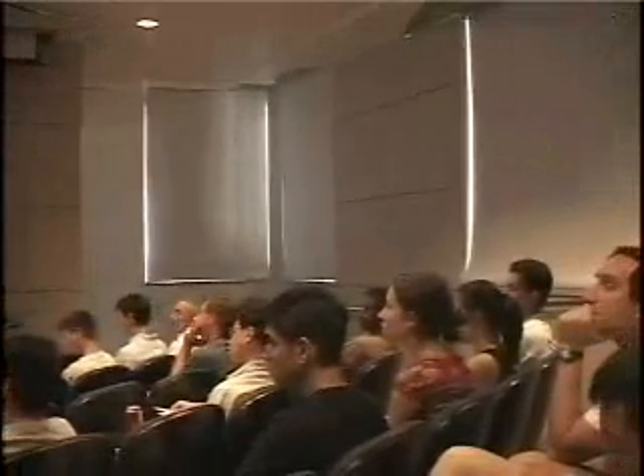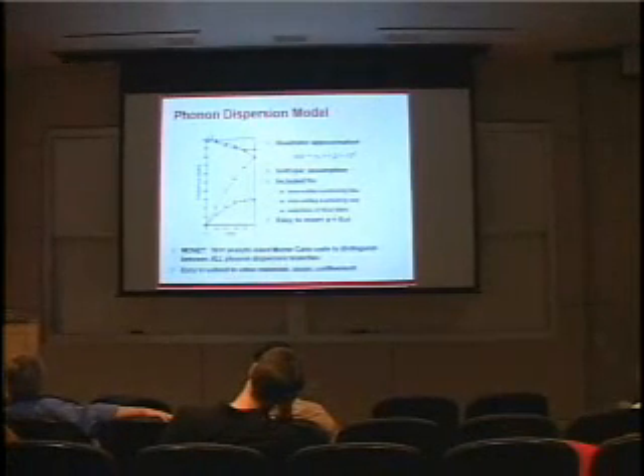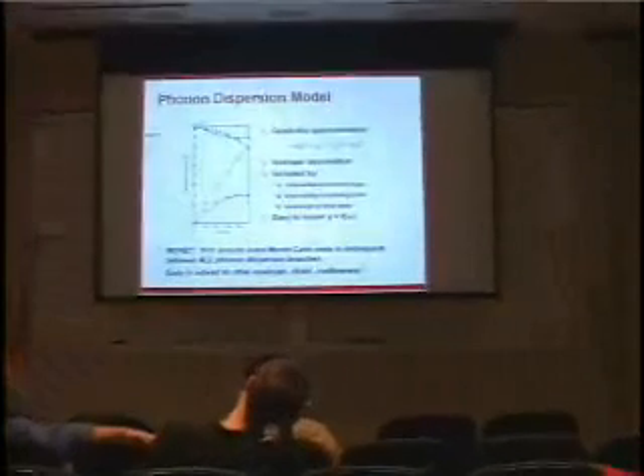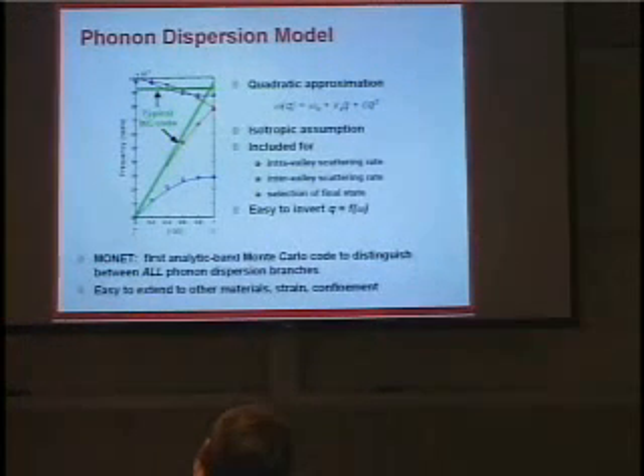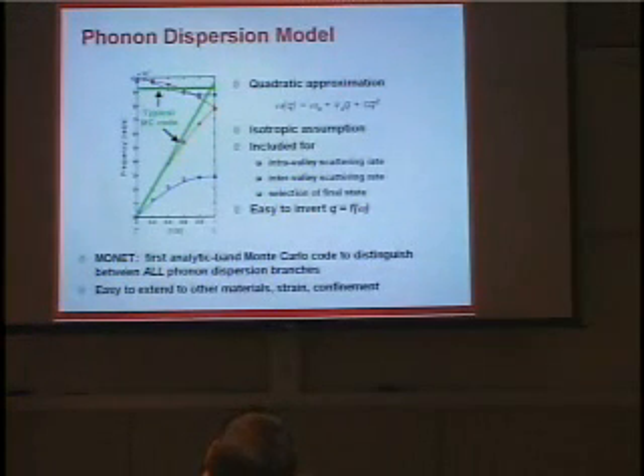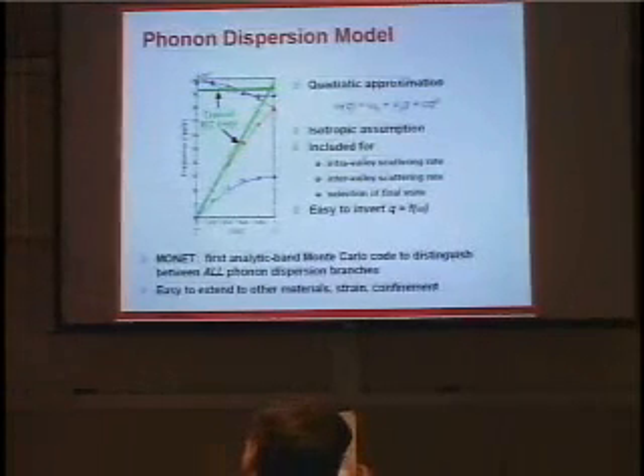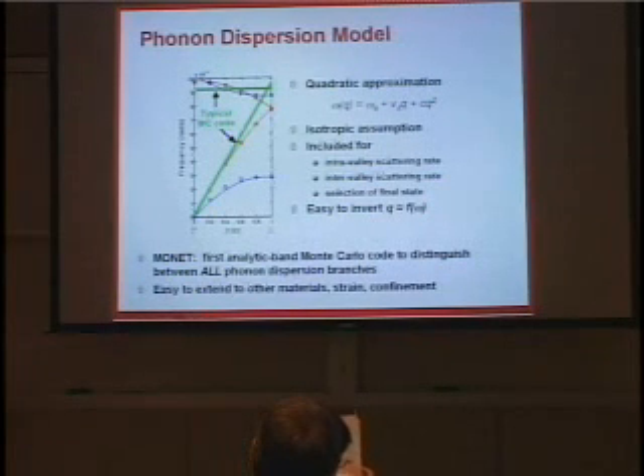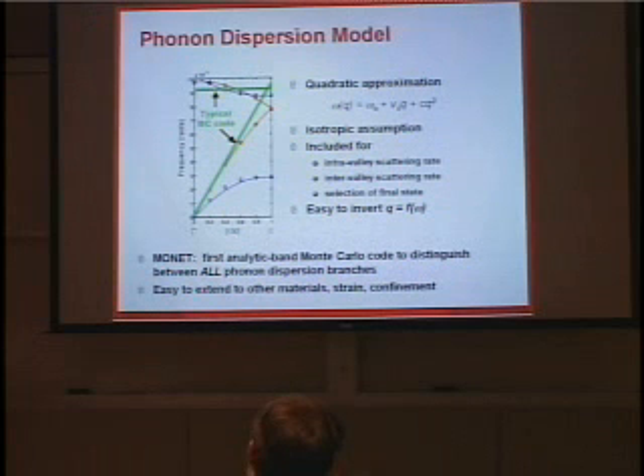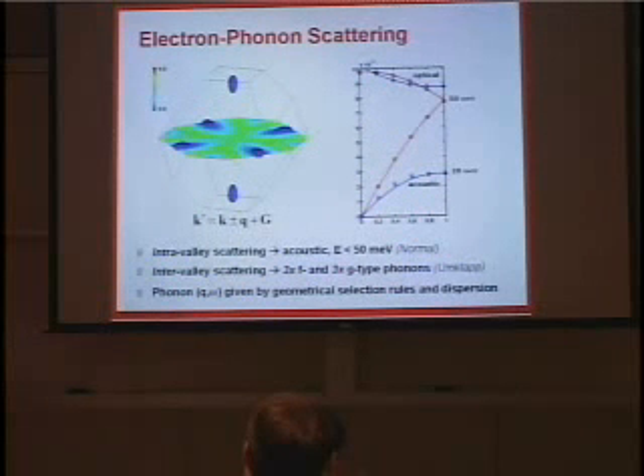And one of the other nice things about the way this problem is implemented is that it's fairly easy to extend this to other materials, to any kind of change in the phonon dispersion due to strain or confinement as well, as long as you have another analytic approximation for the phonon dispersion in those materials. Typical Monte Carlo code, like I was showing a bit earlier, generally uses just simple dispersion for the acoustic modes and a flat single energy for the optical modes. So that's what we're really improving on, especially since we're interested in which phonons exactly are generated, which is what we're working towards. Speaking of which, let's look at the electron-phonon scattering interaction in silicon.